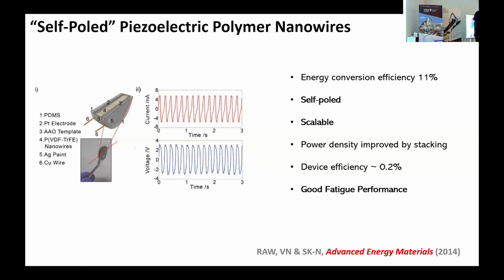In order to do this, you whack the material with a large electric field. It's called poling, electrical poling. You apply a large electric field, which forces all the dipoles along, or more or less along, the direction of the electric field, and then you have yourself a piezoelectric material. Same rules should apply for the polymer. You should have to apply a large electric field. And in fact, for films, people need to do this, except polymers often break down before you can even reach that sort of coercive field that you need in order to get this alignment.